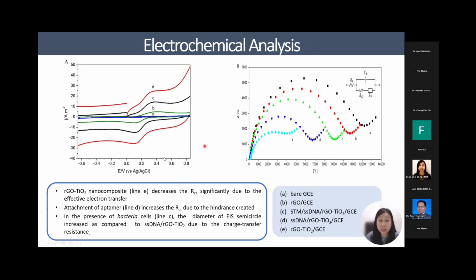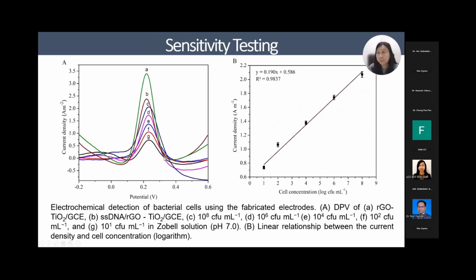So here shows the electrochemical analysis. This is the CV curve, and this is the EIS. The CV measures the current density, and EIS measures the resistivity. You can see here the bare GCE has a very high resistivity. But when we make RGO, even the RGO titanium nanocomposite, you can see the charge transfer resistance decreases significantly due to the effective electron transfer. When we attach the aptamers, it further increases the charge transfer resistance due to the hindrance character. Then in the presence of the bacterial cells, the diameter of the EIS semicircle increases further compared to the one with the aptamers, due to the charge transfer resistance. So this EIS result is comparable with the CV.